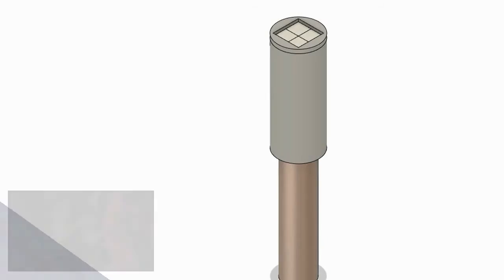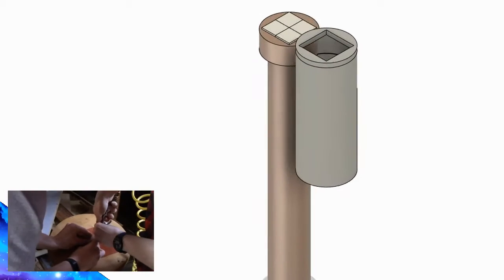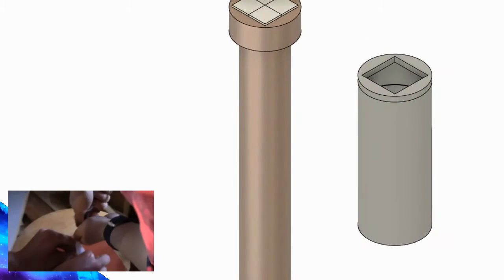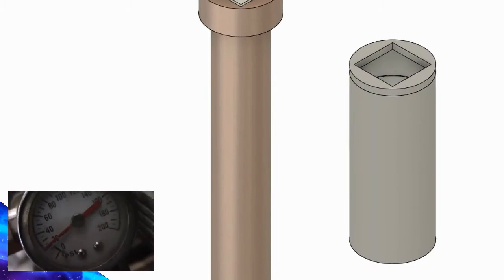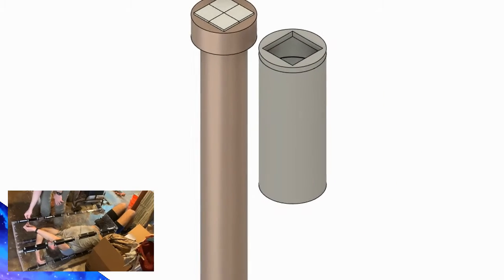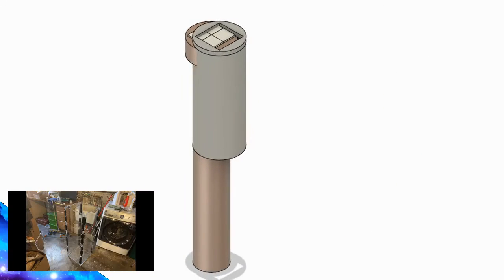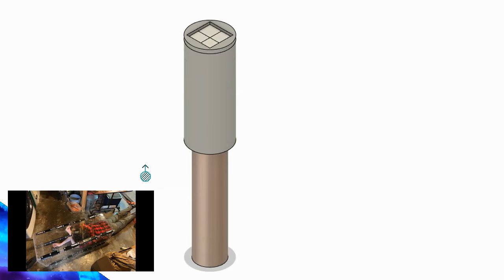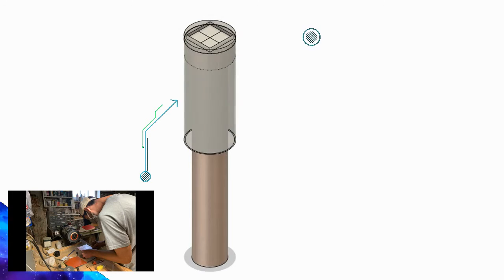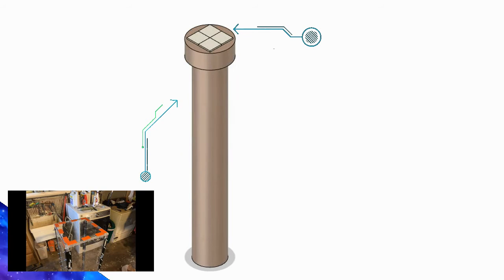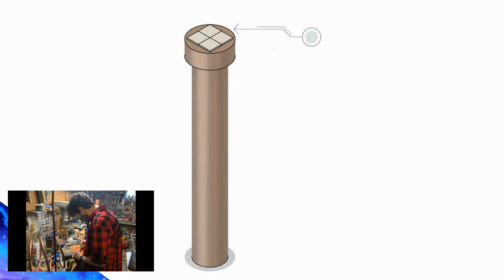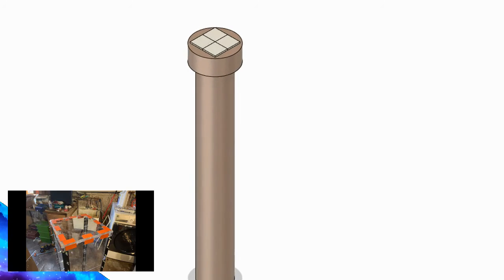The original design used aerogel to insulate the HTB and radiator cylinders above 20 centimeters, the depth where temperature stabilization starts. However, due to shipping delays, we used ceramic fiber, which was readily available. Ceramic fiber was installed in two pieces, a thin outer ring between the copper components and steel pipe, and a thick blanket on top that shielded the exposed areas of the HTB from the heat lamps.